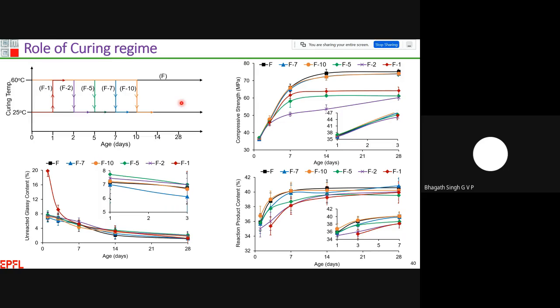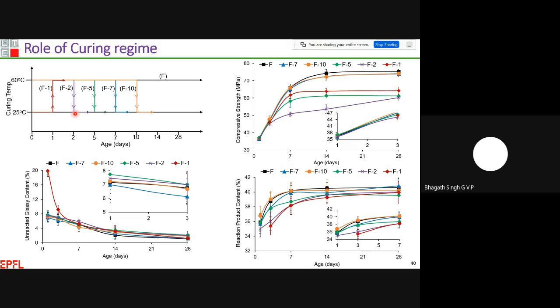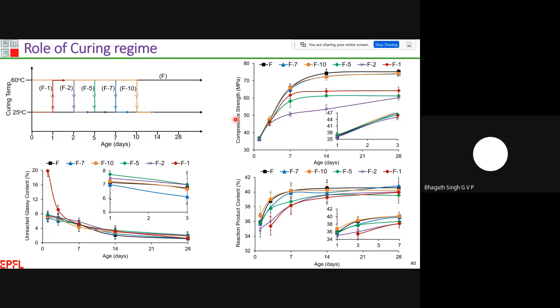We also examined the role of curing time at two different curing temperatures. This is the schematic representation of the curing schedules we used in our research. We used two different curing temperatures, 25 and 60 degrees Celsius. F1 indicates that we cured the samples for one day at 25 followed by 60, and F2 indicates 2 days at 25 followed by 60 for the remaining curing time. We wanted to see whether there is any change in the morphology, the product type, or the glassy dissolution. We want to identify what happens if we change the temperature, because in real-time applications we can see a clear difference between daytime and nighttime temperatures in our locality.